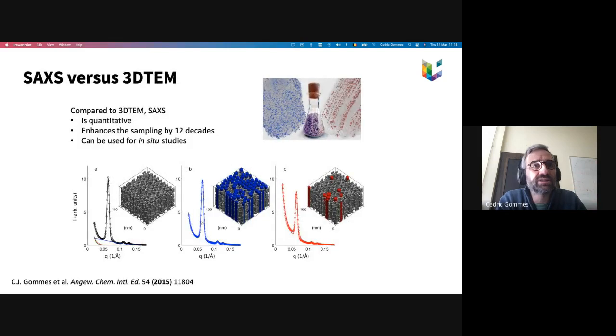And by doing that, in the end, you're able to quantitatively describe the scattering patterns just in terms of that single parameter that tells you whether the active phase inside is in a few pores or homogeneously distributed. And if you combine these small-angle scattering with 3D TEM, of course it's quantitative now because we have a model, and the striking thing is it enhances the sampling by 12 orders of magnitude compared to microscopy.